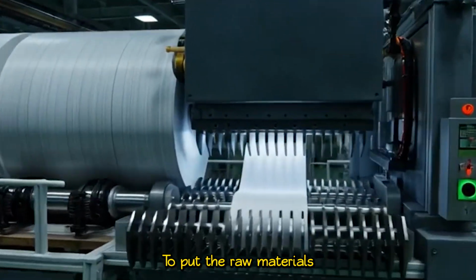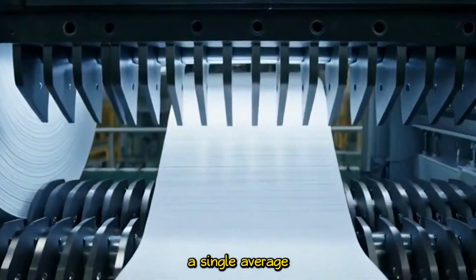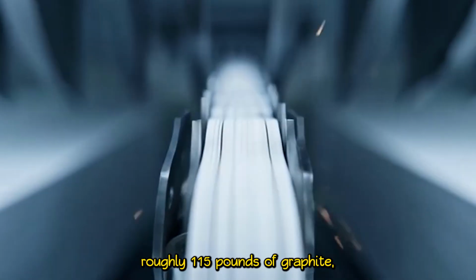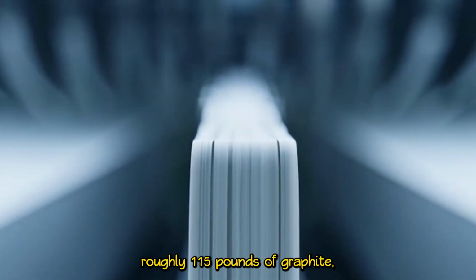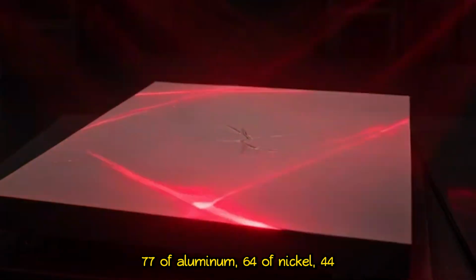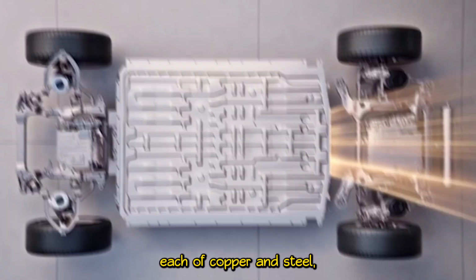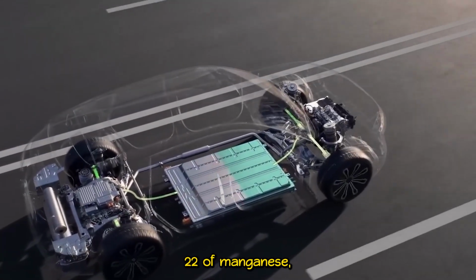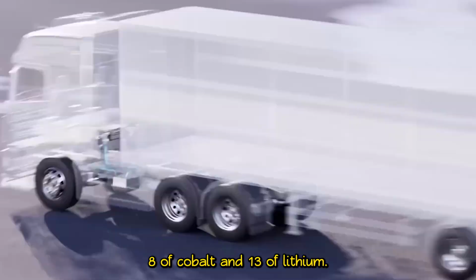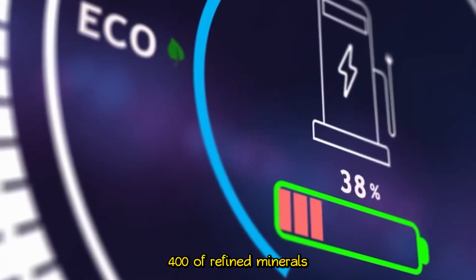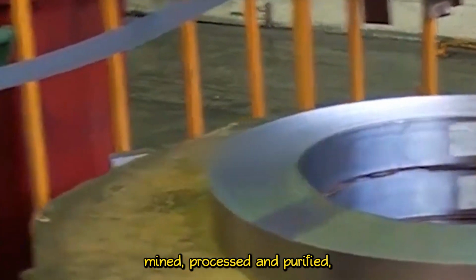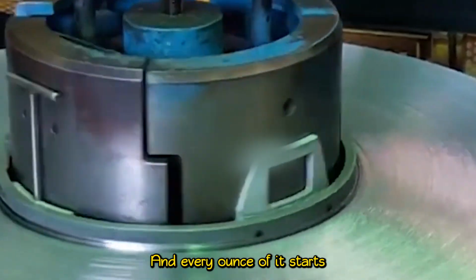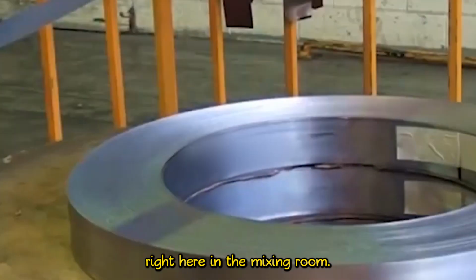To put the raw materials into perspective, a single average EV battery with a 60 kilowatt-hour capacity contains roughly 115 pounds of graphite, 77 pounds of aluminum, 64 pounds of nickel, 44 pounds each of copper and steel, 22 pounds of manganese, 18 pounds of cobalt, and 13 pounds of lithium. That's over 400 pounds of refined minerals mined, processed, and purified, packed into every single battery. And every ounce of it starts right here in the mixing room.